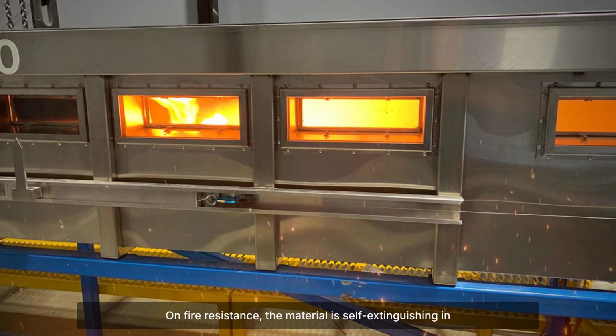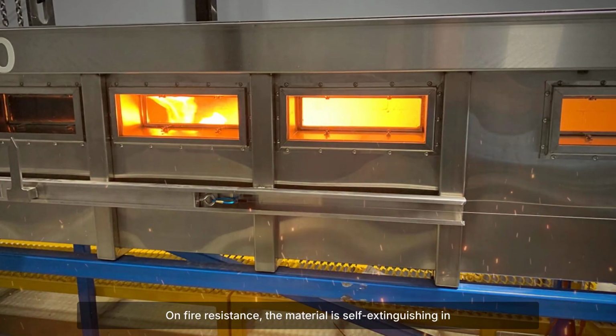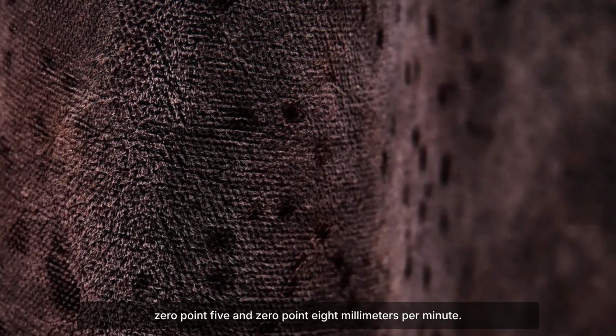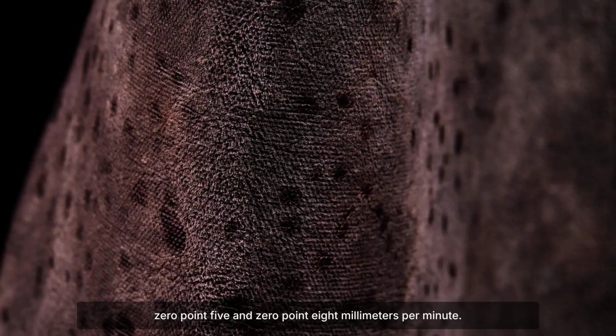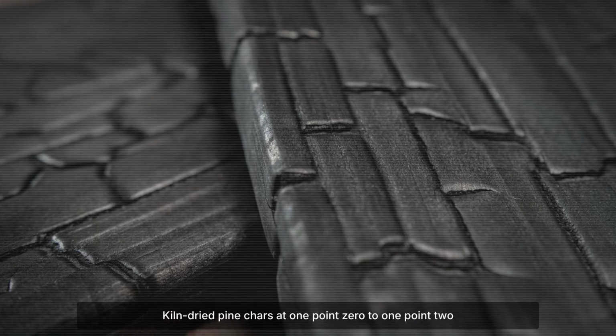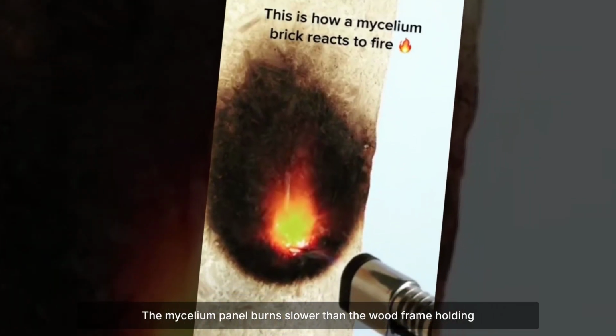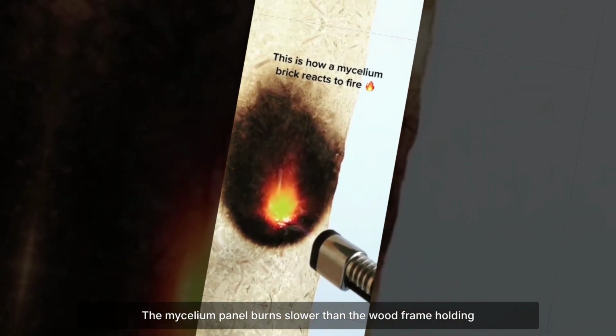On fire resistance, the material is self-extinguishing in ASTM E84 surface burning tests, with a char rate between 0.5 and 0.8 millimeters per minute. Kiln-dried pine chars at 1.0 to 1.2 millimeters per minute. The mycelium panel burns slower than the wood frame holding it.